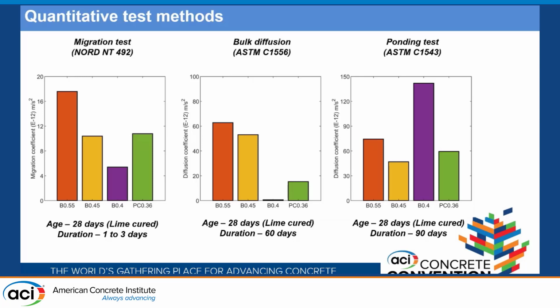and specifically if we look into the result of 0.4 water cement ratio for BCSA, so B.4 is BCSA with 0.4 water cement ratio, you can see that for one case, bulk diffusion, it is having a very low diffusion coefficient, but when we have the ponding test, it is totally opposite, it's very high. So one thing we need to look into specifically is the duration of the test method. The migration test period is 1 to 3 days, but for the bulk diffusion test it's almost 60 days in my case. Okay, minimum should be at least 56 days.